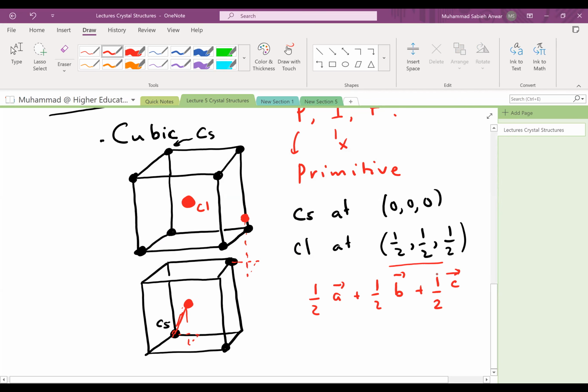And all the lattice points have to be totally equivalent. Lattice points are related by translational vectors. So this is really a primitive Bravais lattice with cesium and chlorine forming the duet of these atoms forming a motif, and they are placed with the proper orientation with a relative vector which I've written in red over here at each lattice point. Okay, so you get this.